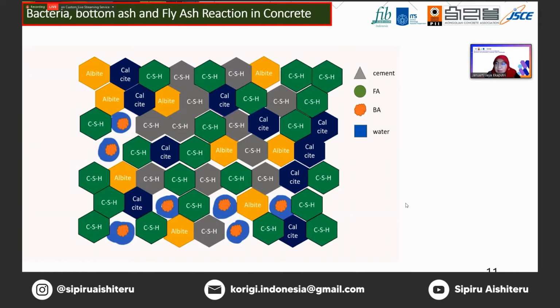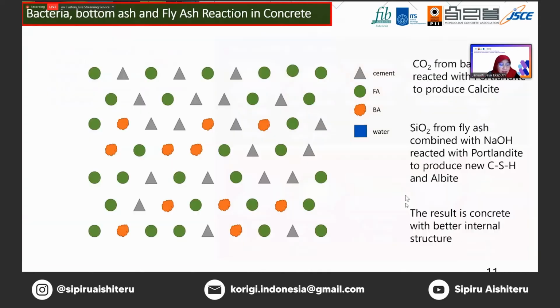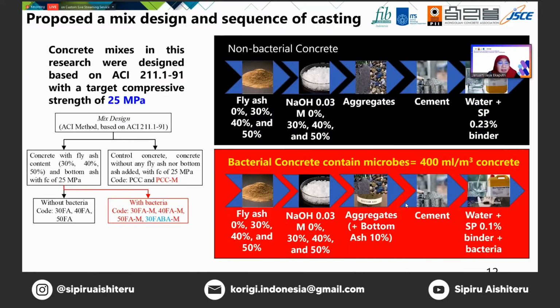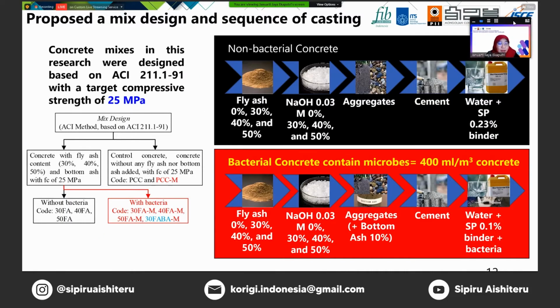In the next slide, in our experiment, we use a mix design to obtain a strength of 25 megapascal in 28 days. As a cement replacement, class F fly ash was used at 40% and 50% by cement weight. Bottom ash was used to replace only 10% of binder weight, but it's actually quite a high amount.